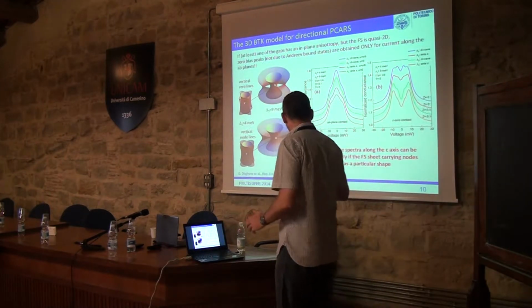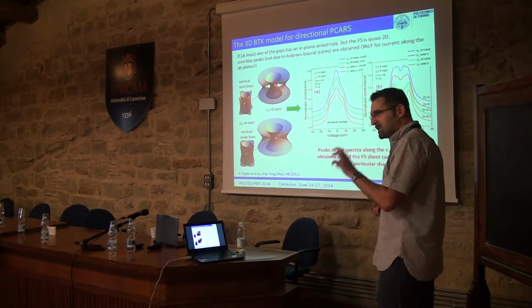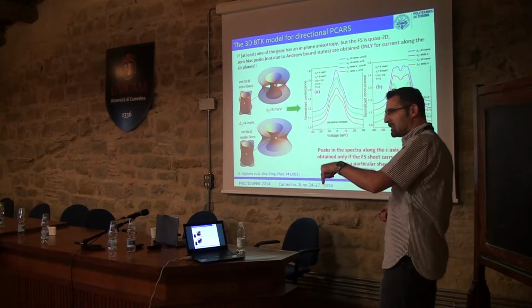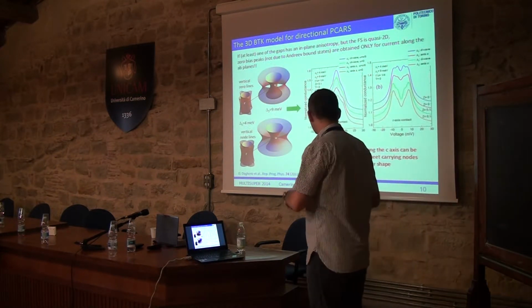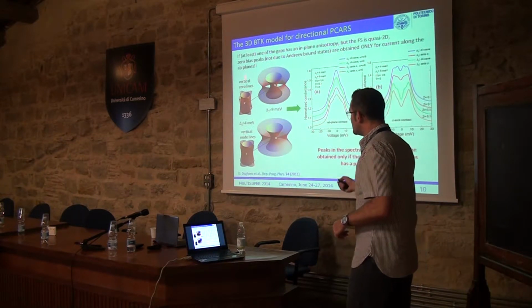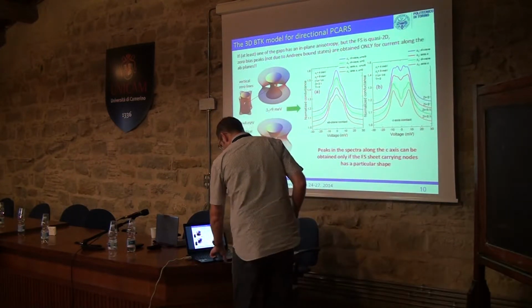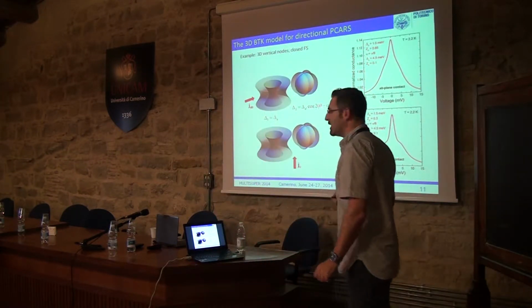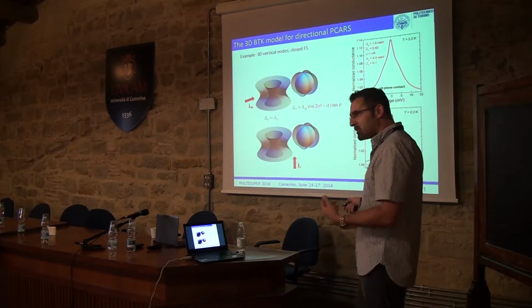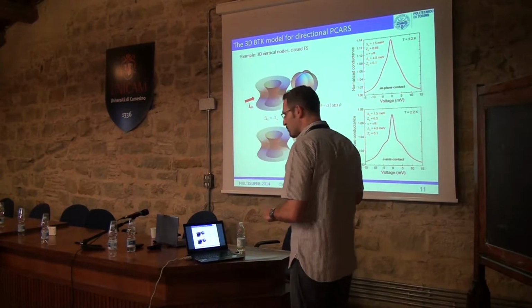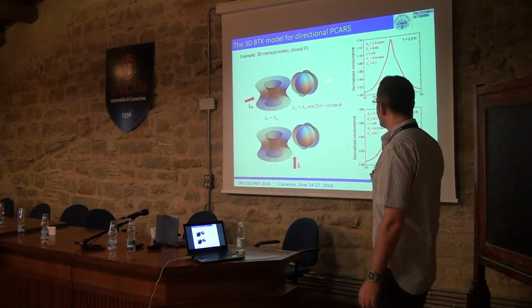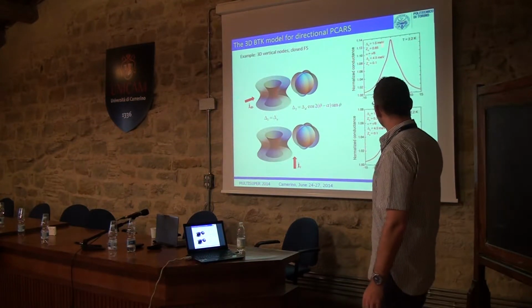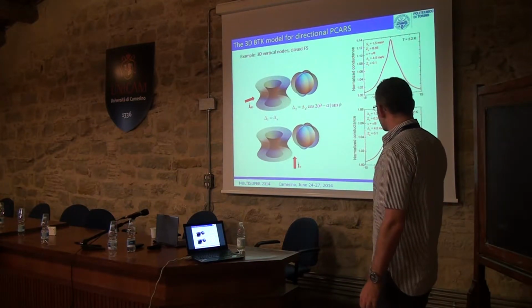So, if we observe peaks in the experimental spectra for injection along the c-axis, and this is the case I will show you later, this means that for sure we are not in this condition. Rather, the condition could be something similar to this one. If the Fermi surface that hosts the anisotropic gaps is closed, is completely 3D, then you have peaks both along the ab plane and along the c-axis, like this.